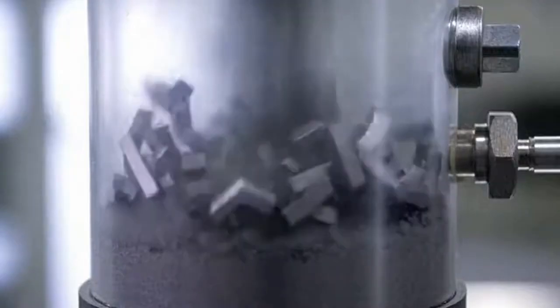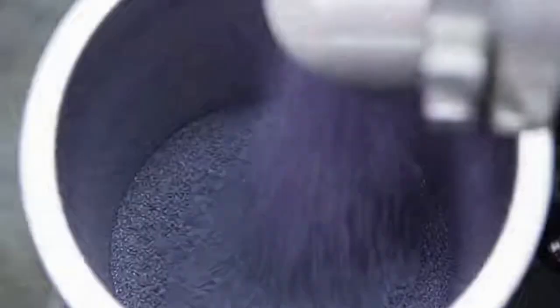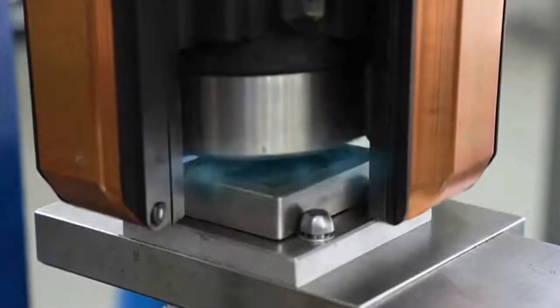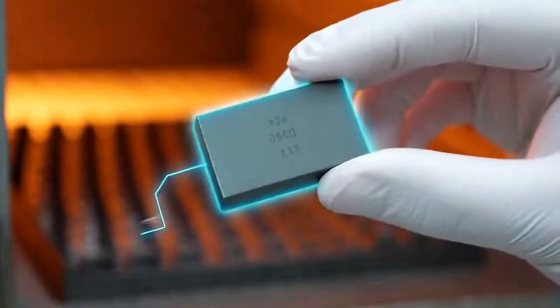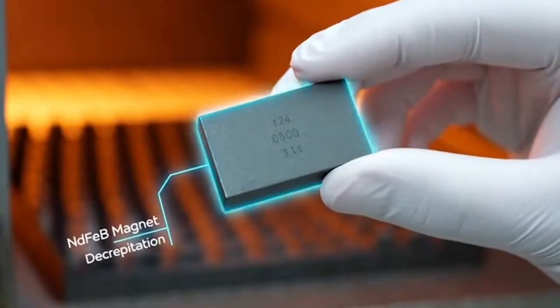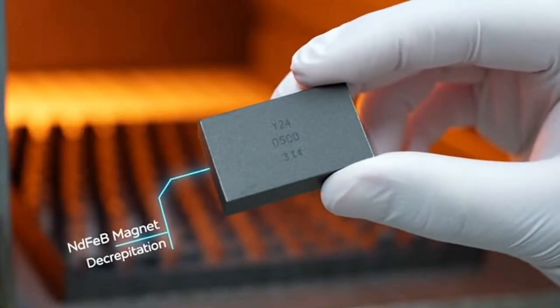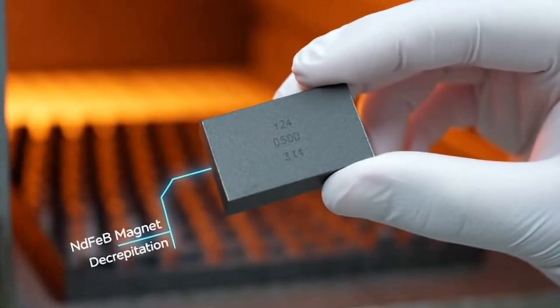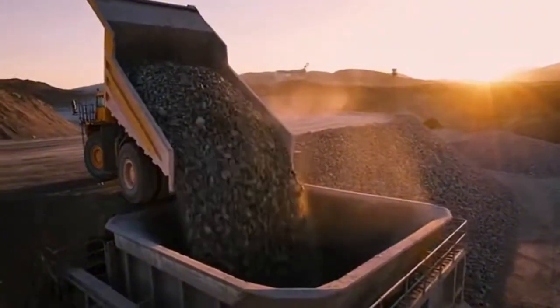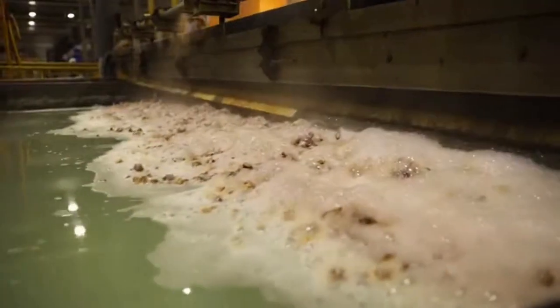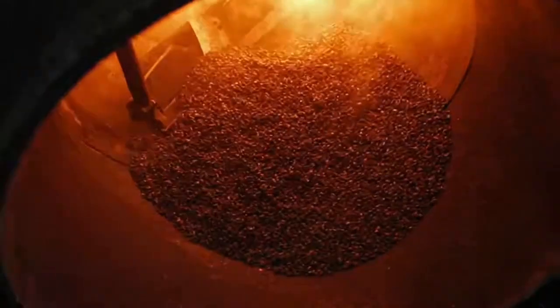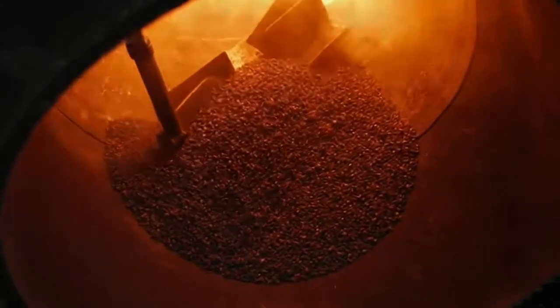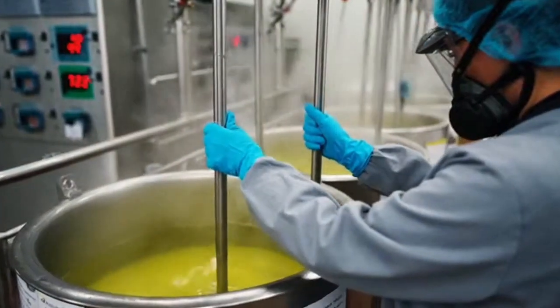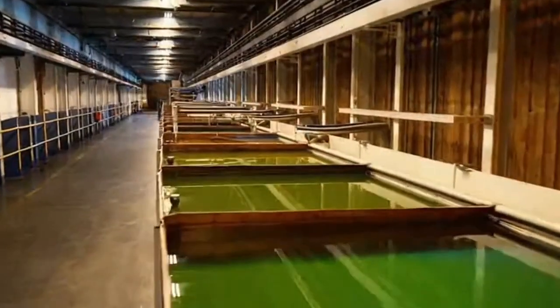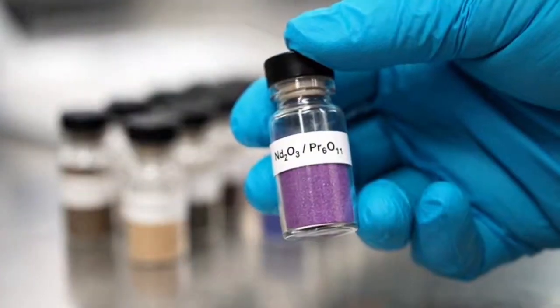The concentrate that comes out of flotation is improved, but still far from pure, useful in the way flour is useful before it becomes bread. So you roast the concentrate, driving off the carbon dioxide and neutralizing the fluorides that would otherwise devour your equipment or resist leaching. Now the rare earths in the ore are in a more amenable mood for strong acids. You leach the roast with acid, dissolving the rare earths into that pregnant solution we talked about.